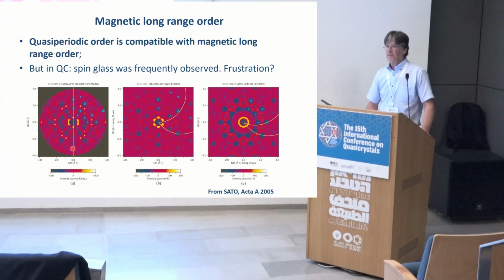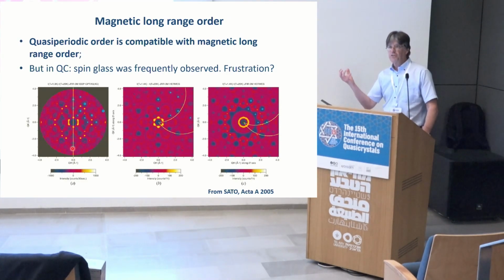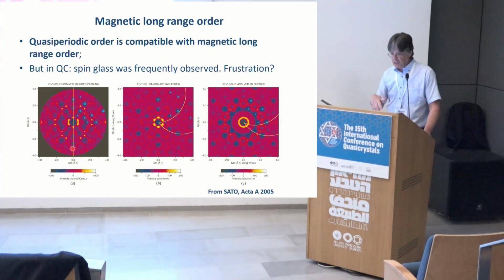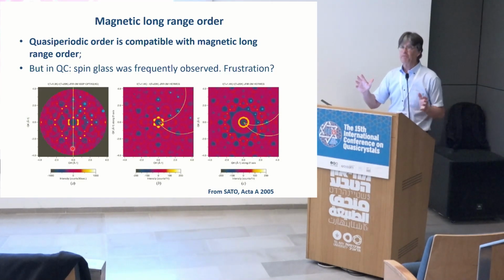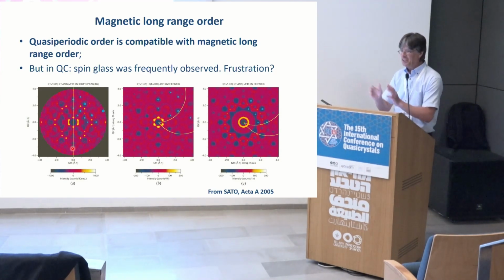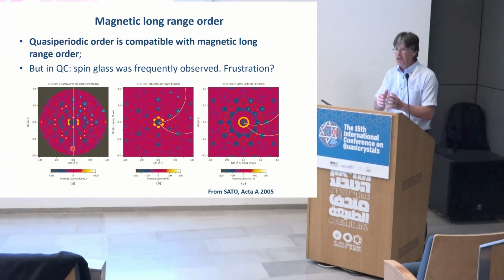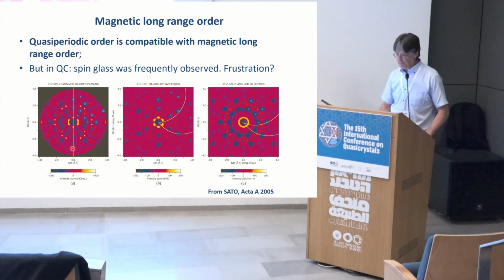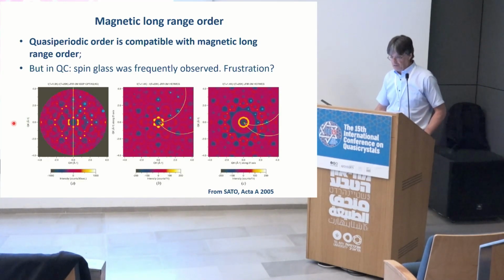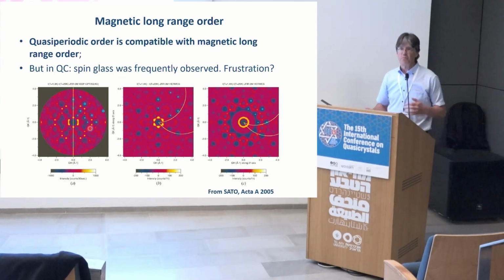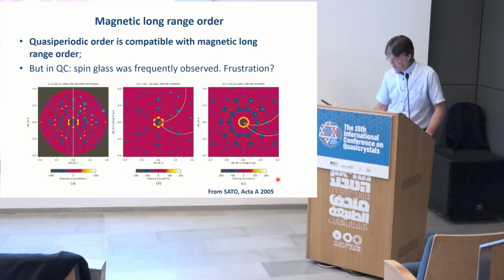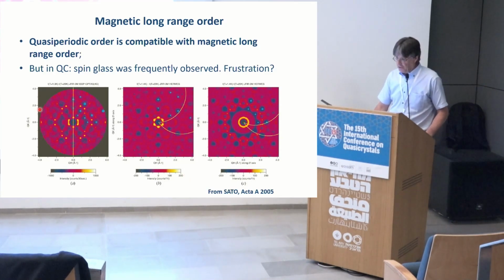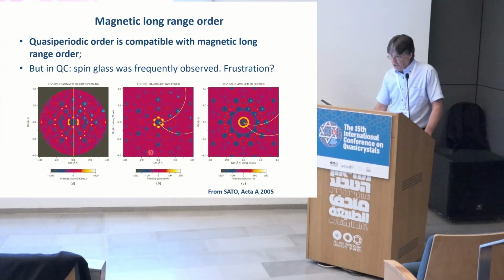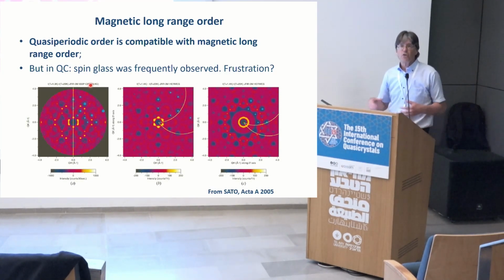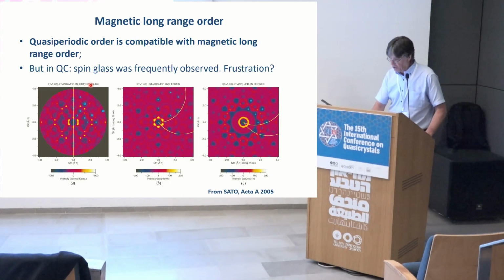Another long-time question was, is it possible to have a magnetic long-range order? In principle, quasi-periodic order is compatible with magnetic order. There is no reason not to. And Ron has derived all the space groups that are compatible with quasi-periodicity and magnetism. But for many years, only spin glass, which means short-range order, has been observed. So it's a nice magnetic scattering pattern taken from the work of Taku Sato on zinc-magnesium-rare earth systems, and only short-range order was observed. And the question was, is it really feasible to have a long-range magnetic order?